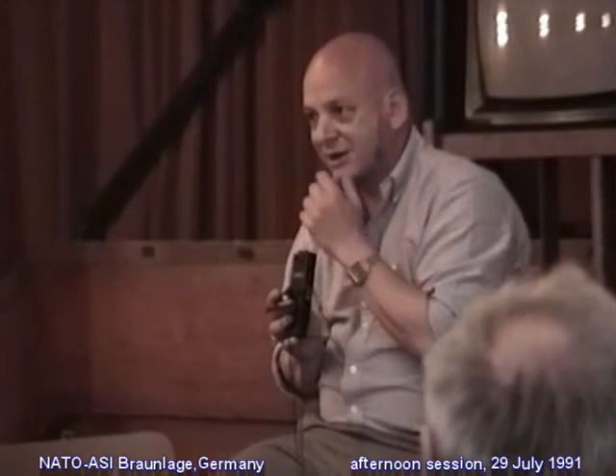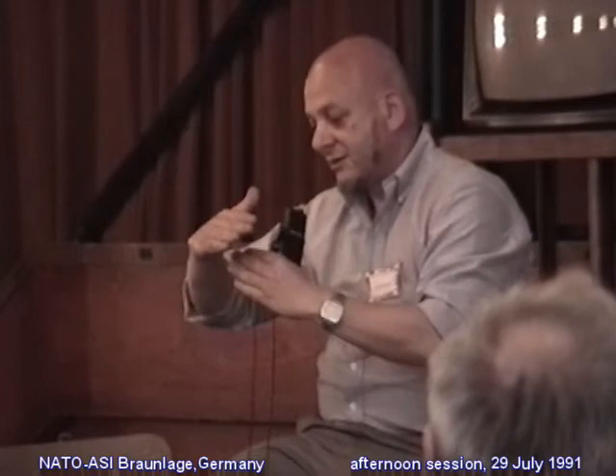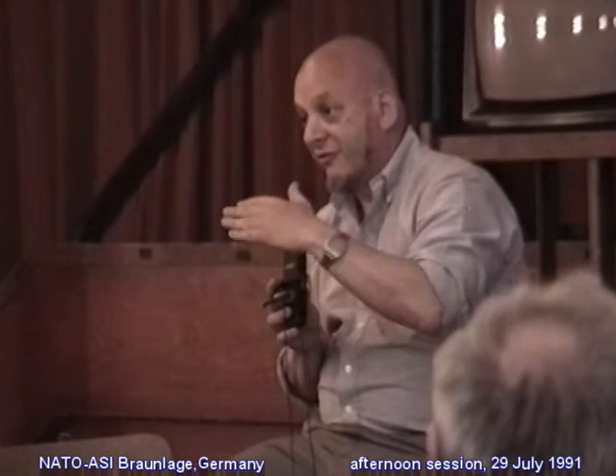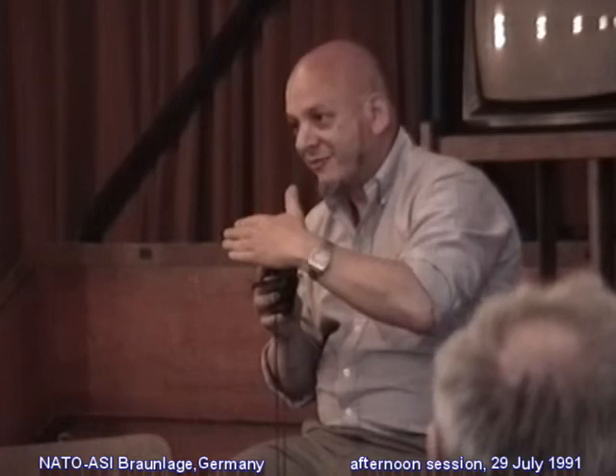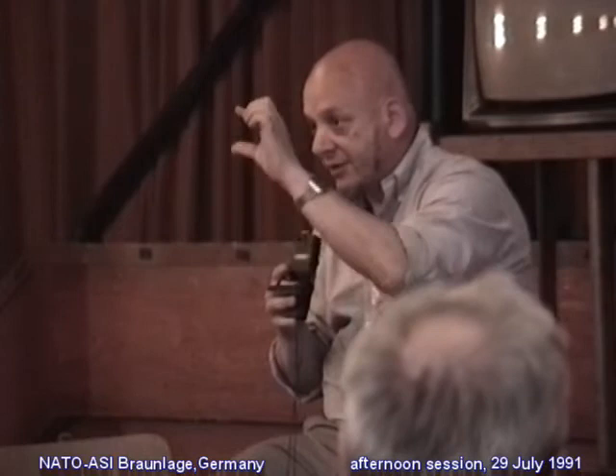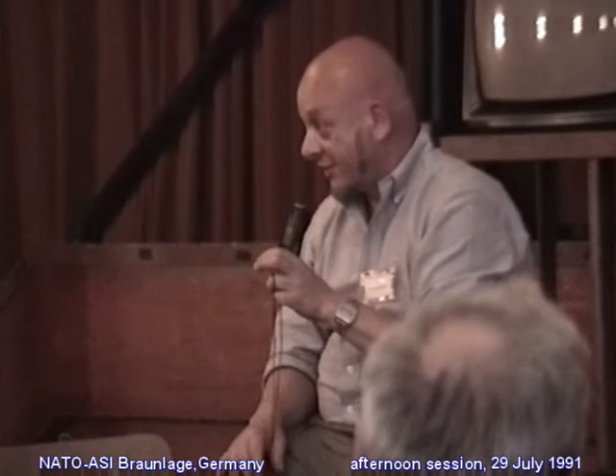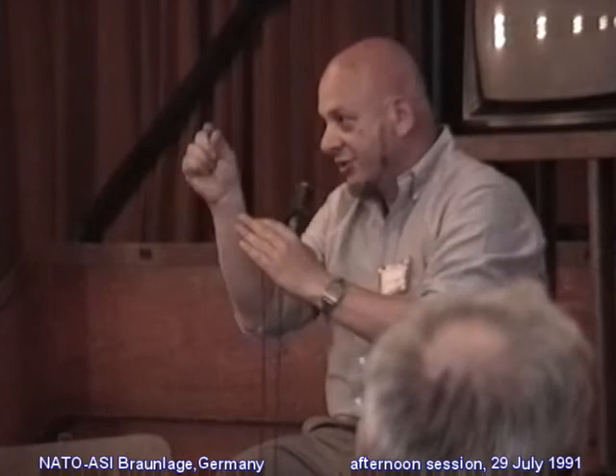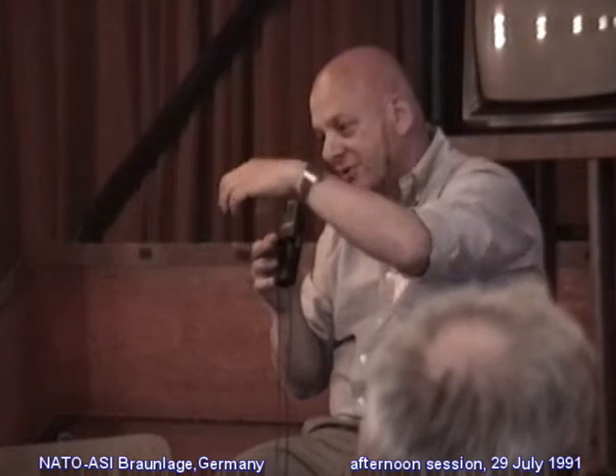The other comment has to do with the comment that my good friend Jacob made with regard to David Tabor's suggestion. And Jacob's right that surfaces do snap. And it's very difficult to avoid these catastrophic fast events, no matter how slow you separate the two things. There will be a point of instability where, say, two angstroms of lattice spacing will be jumped in a picosecond. This will give a sound wave propagating. However, it's not necessary that the whole surface will separate as a uniform zone. It could develop these little necks, little cones. And those can be done very slowly. Those will reorganize themselves in a slow way. And eventually, it will come to the point of snapping maybe the distance between only two atoms.